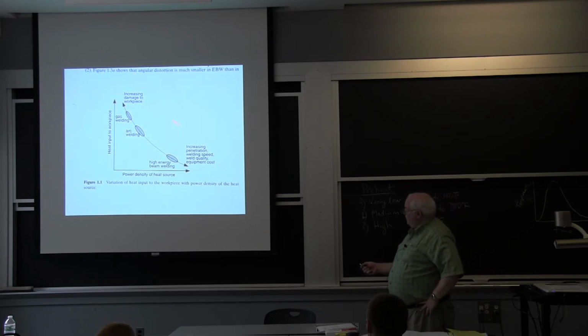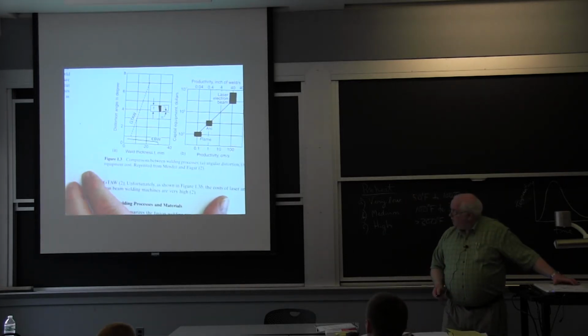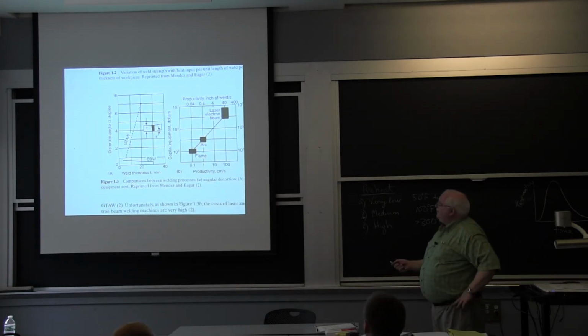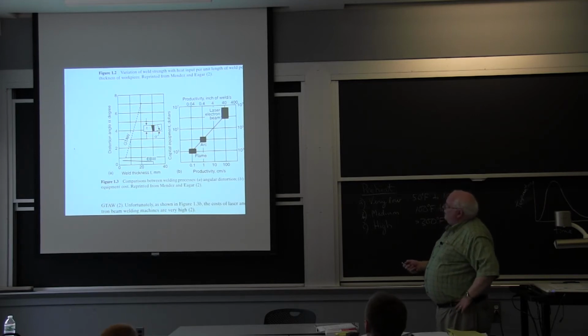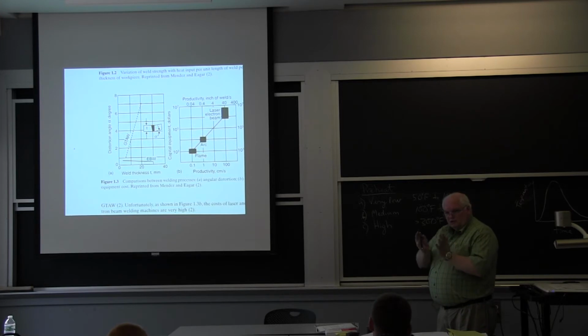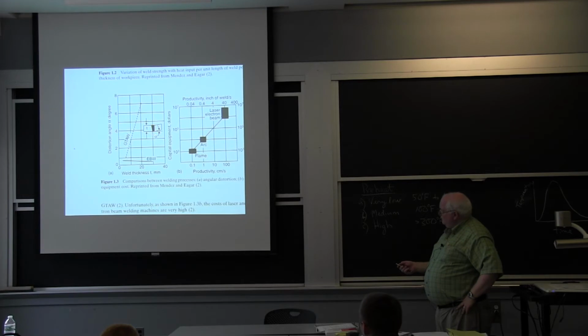So if you want to look at density of the heat source versus distortion, you'll find that it varies in that manner. And here's something else out of his book, which is looking at gas tungsten arc welding, which is an arc welding process, makes a very V-shaped weld, versus electron beam welding. The distortion angle alpha goes from near zero to very high values depending on the thickness of the material.